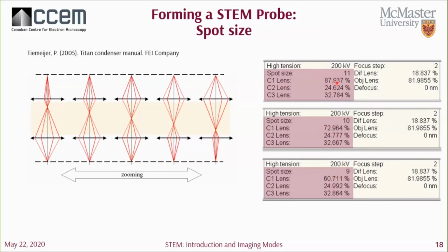They use a system which they refer to as a condenser zoom system, in which the image between the two lenses can be varied, but the image in front of the first lens and the image after the second lens remain in the same position. So in choosing the spot size, the first step is that we actually change all 3 of these lenses, and they work in conjunction so that the image formed after the C3 lens remains fixed. Imagine if you have a C3 lens down here. As we change C1, the position of the image here doesn't change.